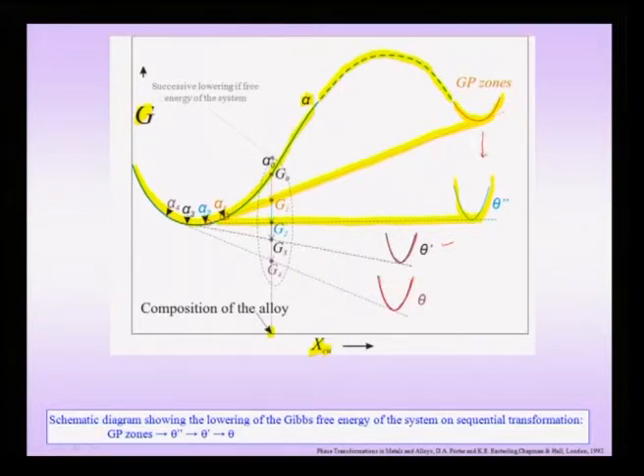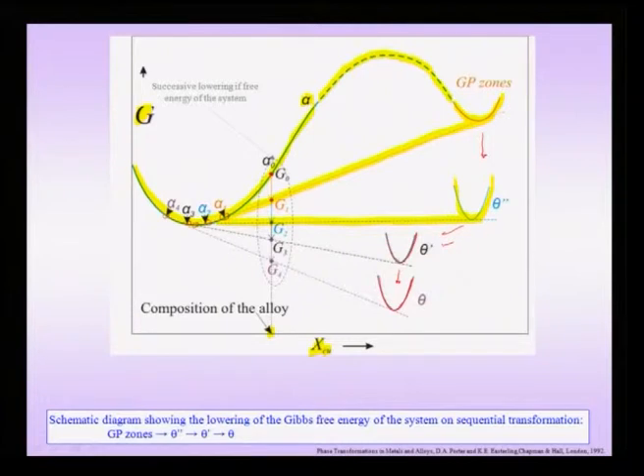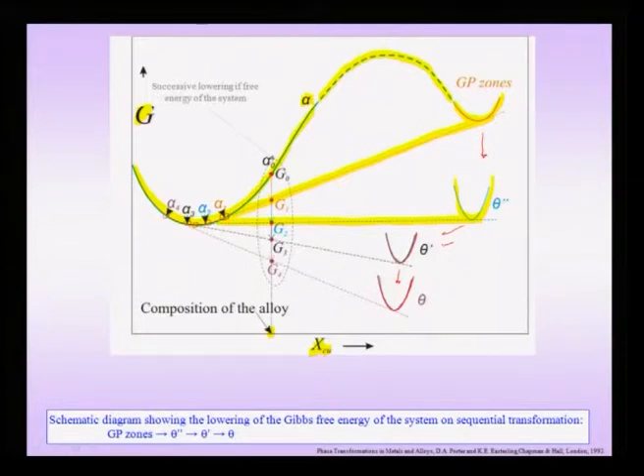The overall direction in which Gibbs free energy moves is downward. At each stage there is a stepwise reduction: G₁ when GP zones form, lower when theta double prime forms, lower still for theta prime, and lowest at the equilibrium theta phase. The question is why metastable phases form — why does theta not directly form from the supersaturated solid solution?